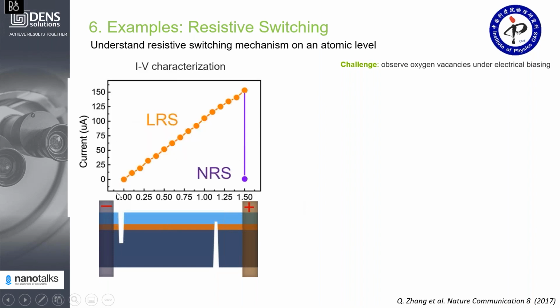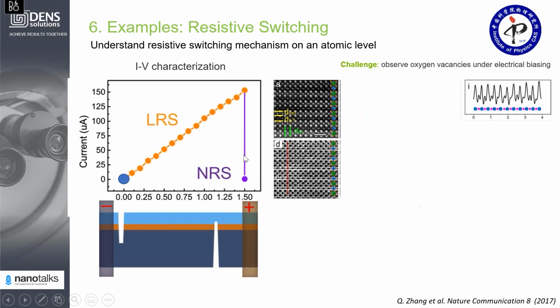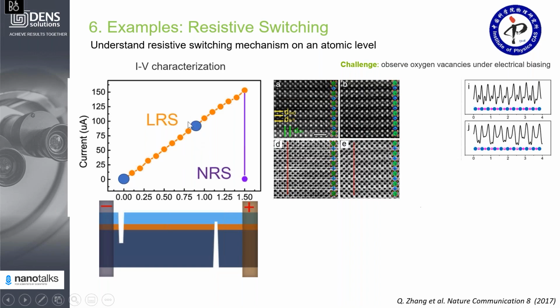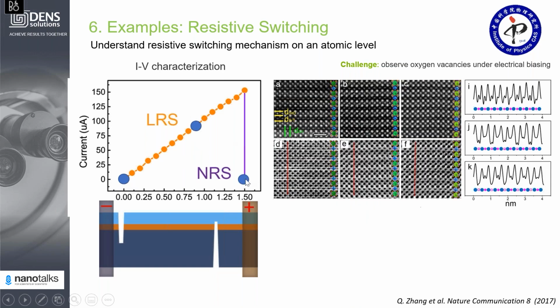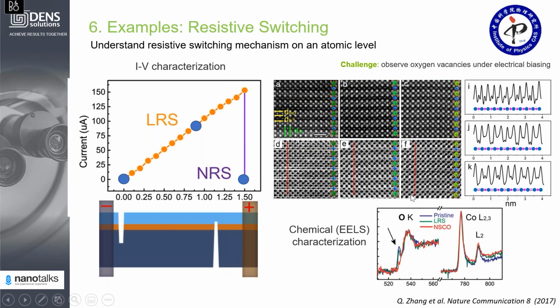Then you do the IV characterization. You apply bias and you measure current and see the resistance. And what the researchers saw is that while applying the voltage, at some point the current drops and the sample becomes more resistive. If you take images at different stages of this process, either in the as-prepared state, somewhere around 0.8 volts, and then in the switched state, first of all, you see that you can do atomic imaging with it. And secondly, from measuring the intensity profile at different stages, you can observe the formation of oxygen vacancies inside the lattice. And of course, you can confirm that using EELS.